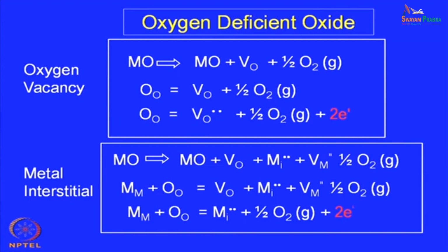So, all non-stoichiometric oxides are related to the point defect concentration, and depending on the nature of the point defect and the kind of non-stoichiometry, you are generating a free electronic charge carrier, which is much more mobile and will give rise to a fairly large conductivity.